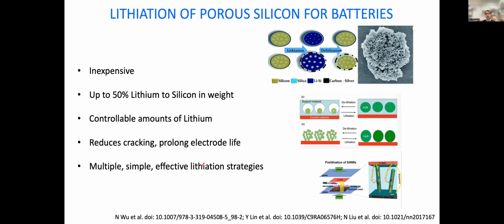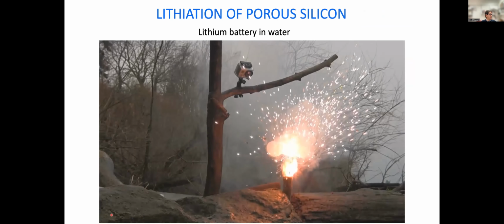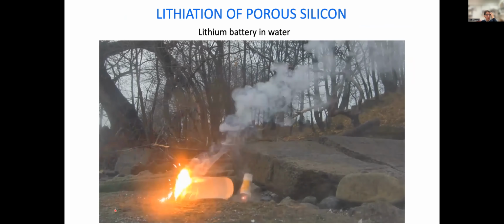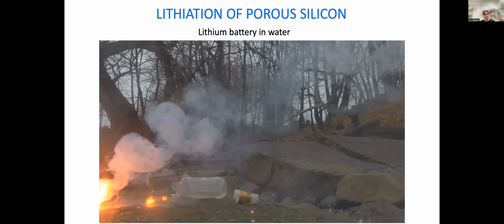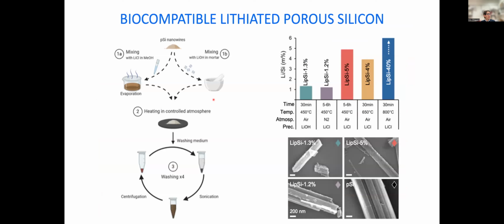The disadvantage of this approach is that this material is not particularly stable when you put it into biological conditions. If you stick lithiated silicon into any aqueous solution, it's very much likely to explode. So what we did is that we developed an approach to lithiate silicon in a way that would be biocompatible. Basically, the main difference to the process of lithiation from batteries is that when we combine the lithium with the silicon and we raise the temperature to make the lithiation occur, we control the atmosphere and we introduce a certain amount of oxidant or a certain amount of nitride, which passivates the lithiated silicon surface.